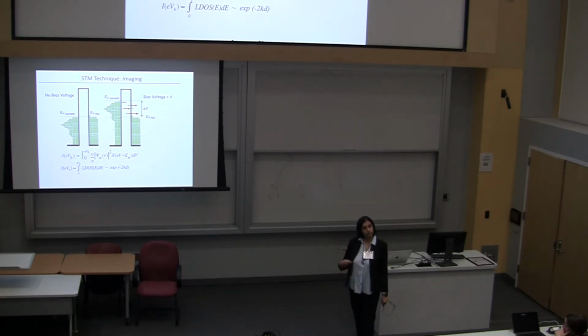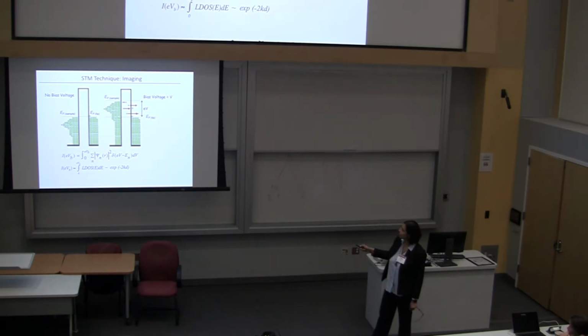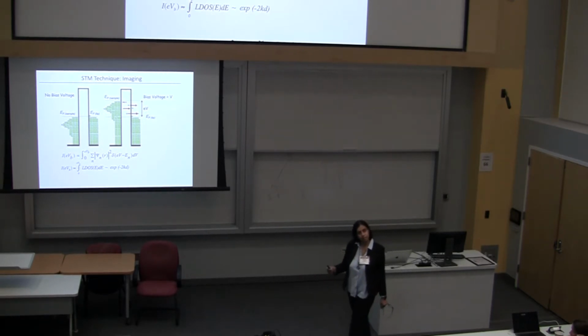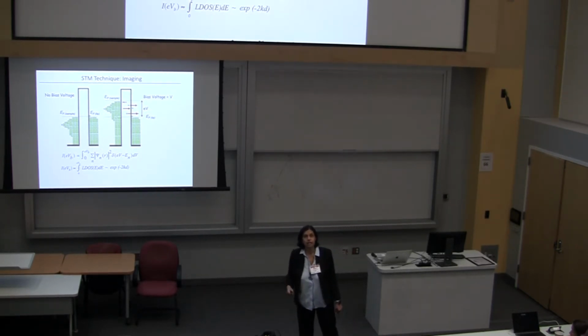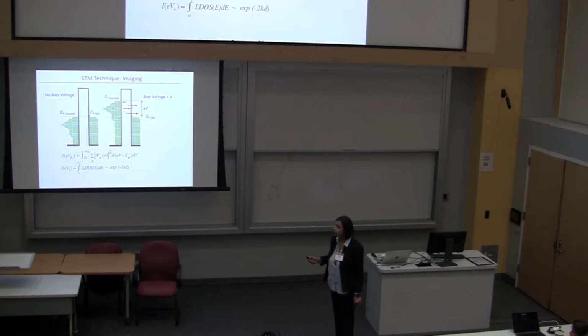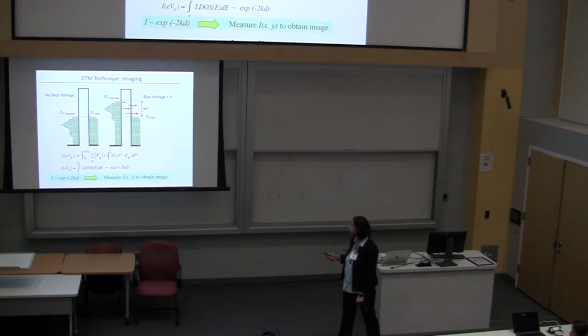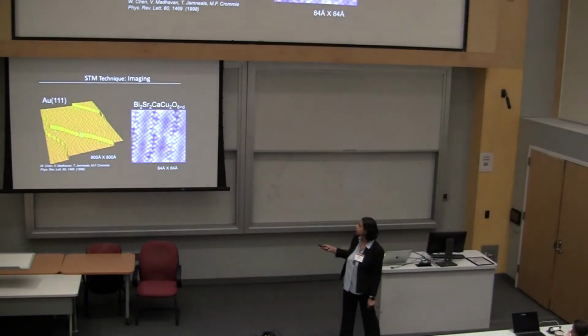So each state is weighted by the square of the wave function. In the z direction, this means the tunnel current is exponentially sensitive to the distance between the sample and the tip. And that exponential sensitivity is what gives us atomic resolution. So then we can get images that look like this.